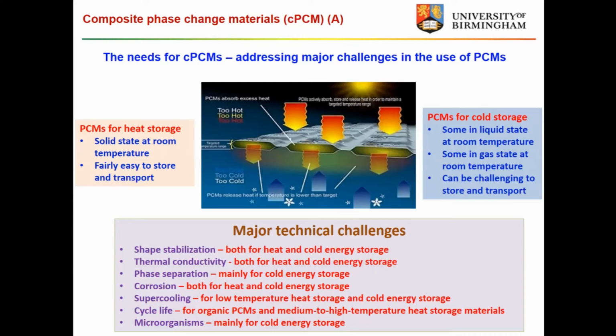Cycling life is also an issue, particularly for organic materials and medium to high temperature heat storage materials as well. We've seen lots of those issues after a couple thousand thermal cycles, and even for the salts for high temperature PCM, we see issues after about 3,000 cycles. Also for cold energy storage materials, there are microorganism issues, growth and mold, and so on and so forth. Those are the issues we have come across. That's just the reason why we needed it.